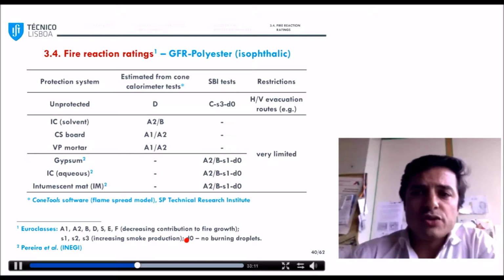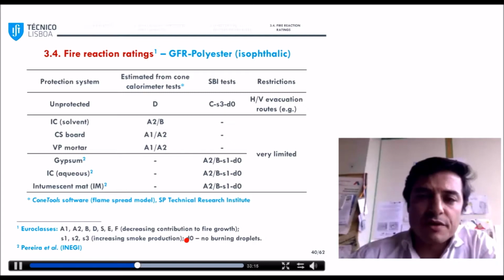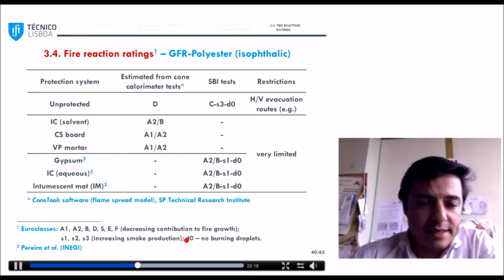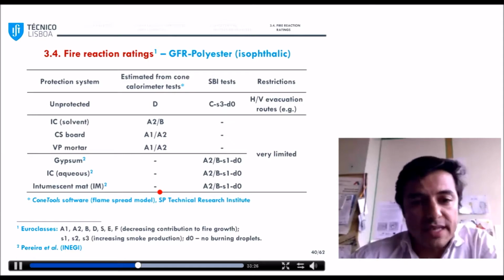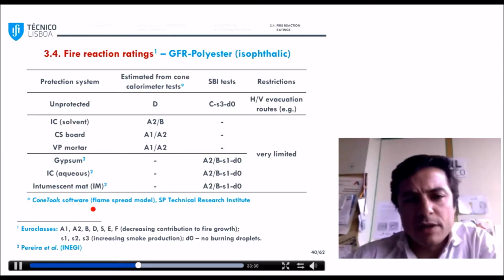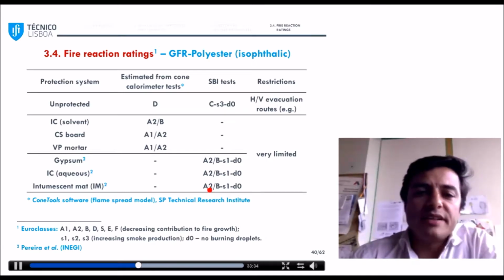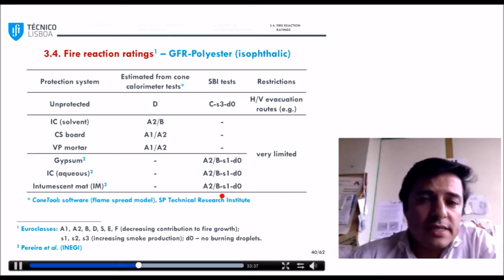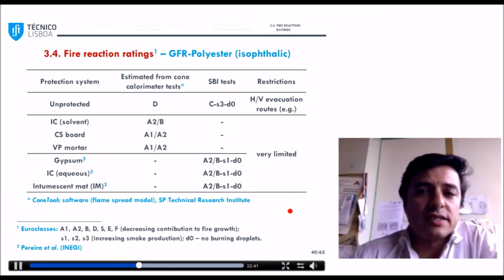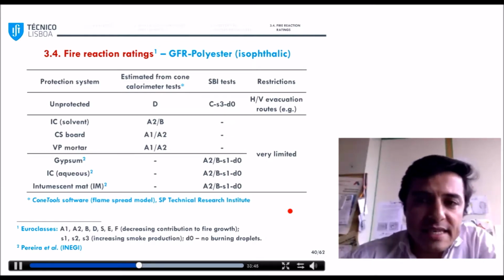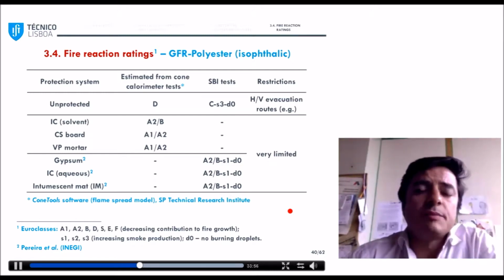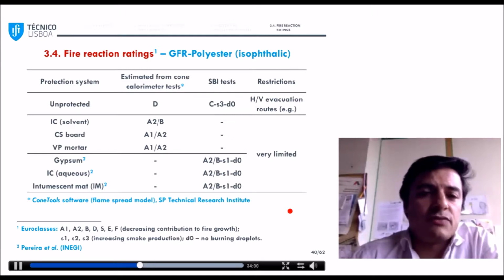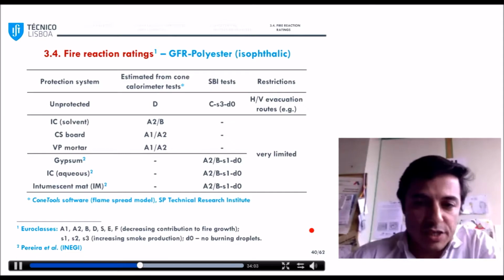So, as a summary, this table shows the European classes of fire reaction for the different fire protection systems that we analyzed in our study. In the second column, the classes estimated from the cone tests using a software based on a flame spread model, and in the third column, obtained directly from the SBI tests. So basically, you can see that without passive protections, the GFRP material is somewhere between classes C to D, which involves some restrictions in terms of building applications, especially in evacuation routes. And with any of the protections, you can see that the performance is substantially improved with classes from B to A, and therefore with much less end-use restrictions.